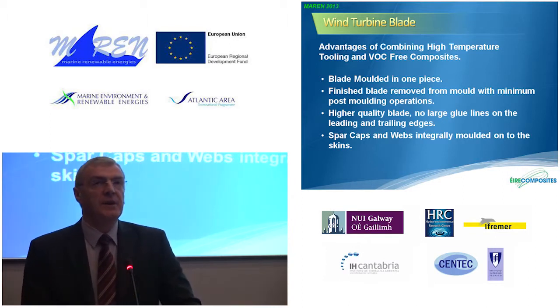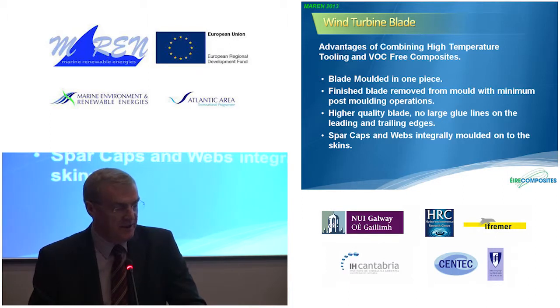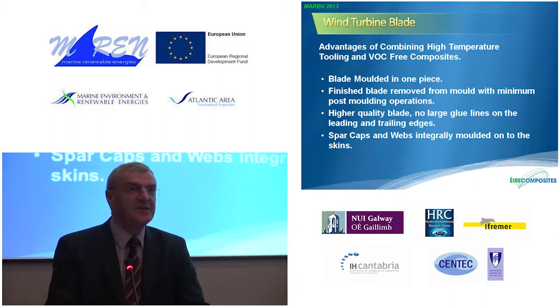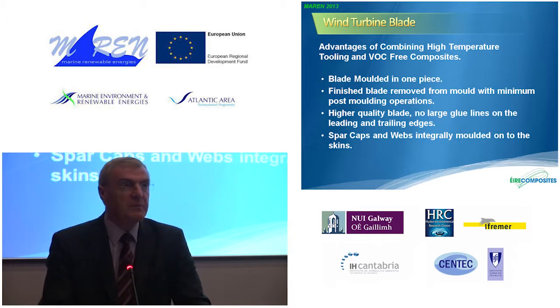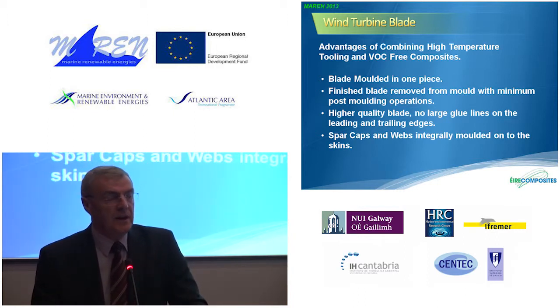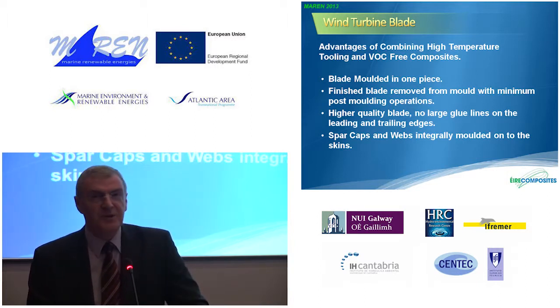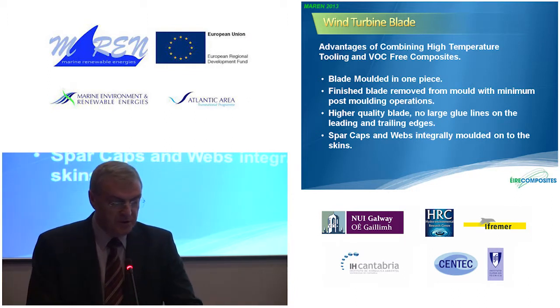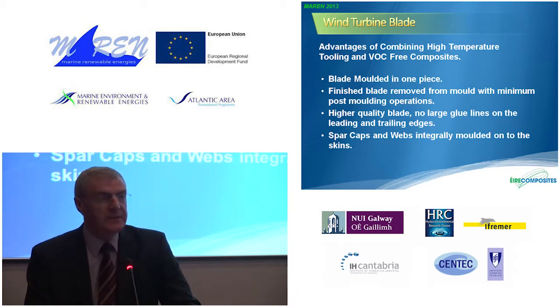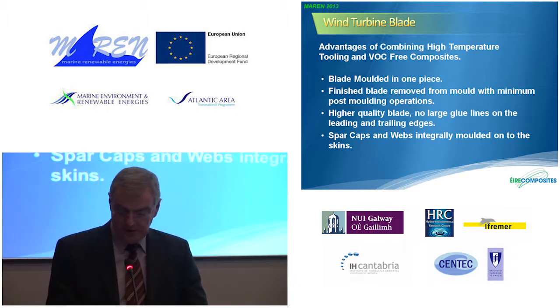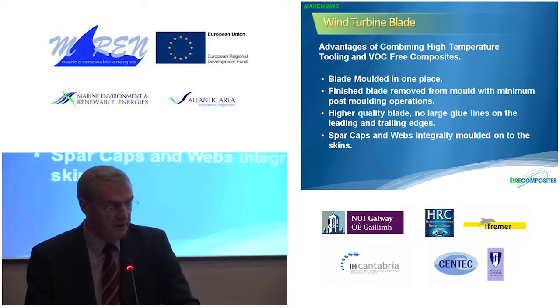The quality of the blade is higher because you don't have any glue or additional materials apart from your composite material, and because you don't have any large glue lines on the leading and trailing edges, it makes for a much better blade. The fibres are continuous through the body of the blade, and so you don't have these areas which are always the areas that cause the most problems and require the most quality control in order to ensure a good product. Also, the spar caps and webs of the blade are integrally moulded, and this results in a much better and stronger blade.